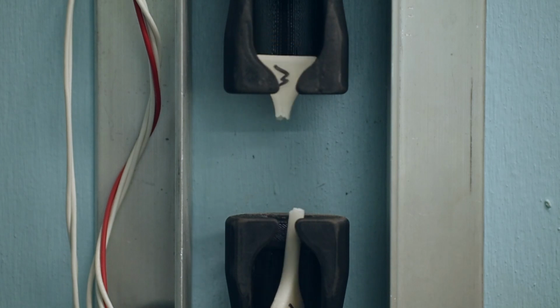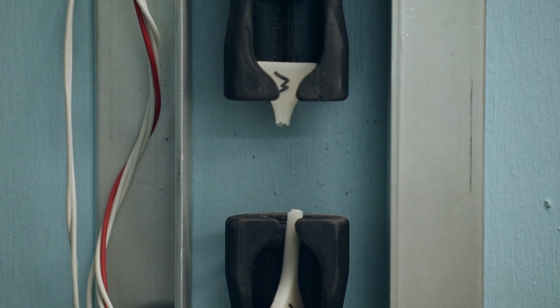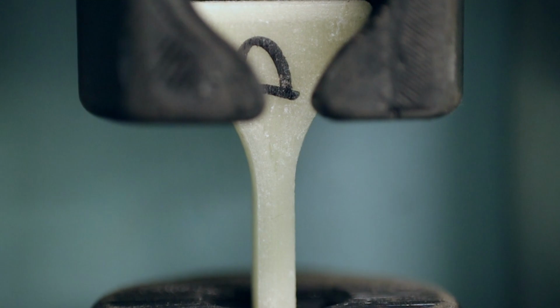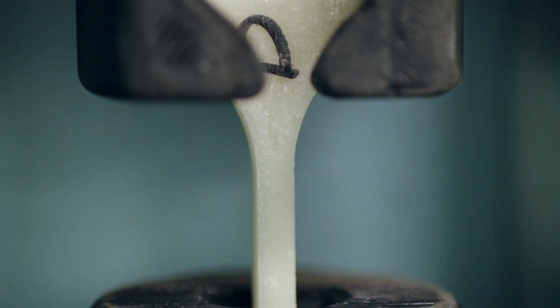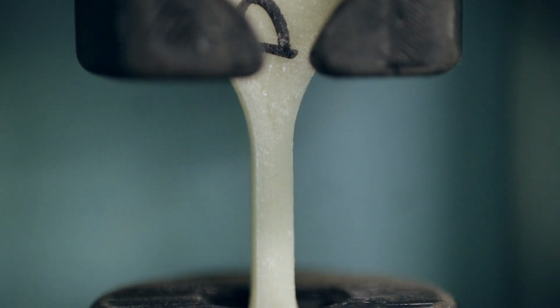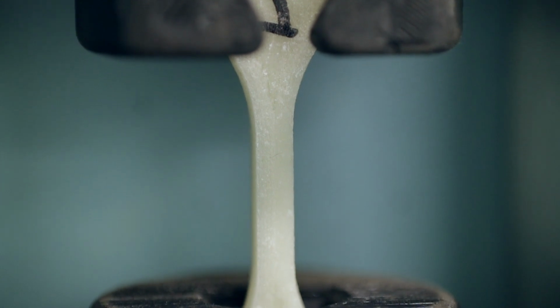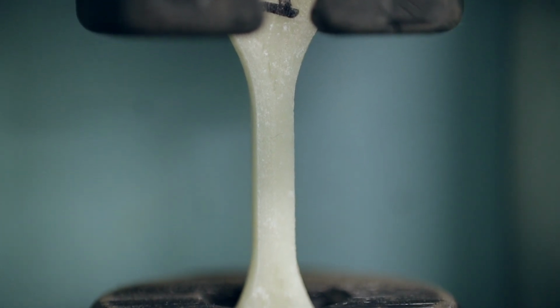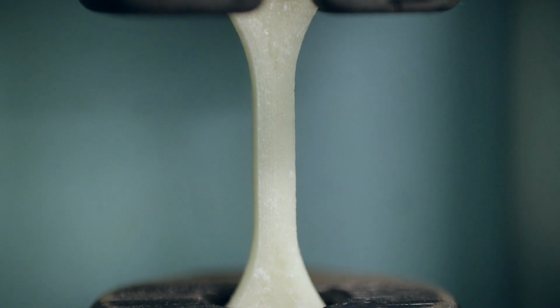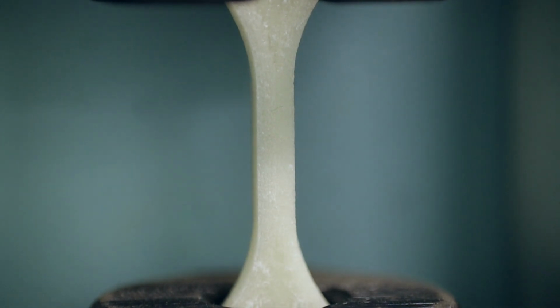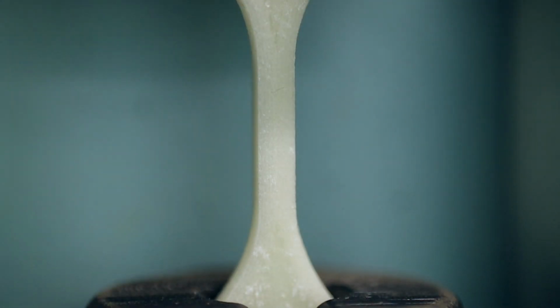Now, I don't have a strain gauge on my tensile tester, unfortunately, so I had to estimate the strain based on how far the machine had pulled the sample. And while this is probably pretty close, it's not going to be perfect, and it's going to have inaccuracies in it. So keep that in mind throughout this test, that the strain values and Young's modulus numbers should be used for comparison purposes on tests I've done with my machine only, and you probably shouldn't compare them to other values because they're probably not that accurate.